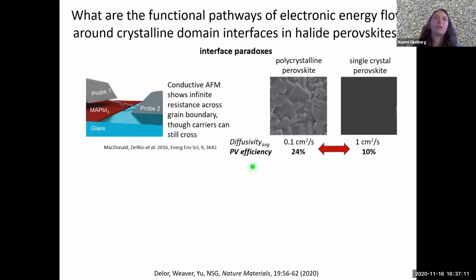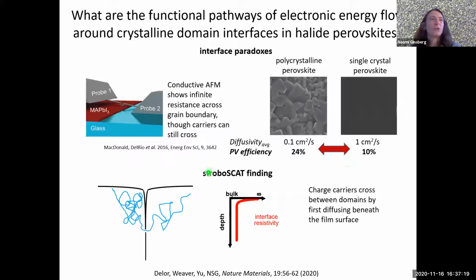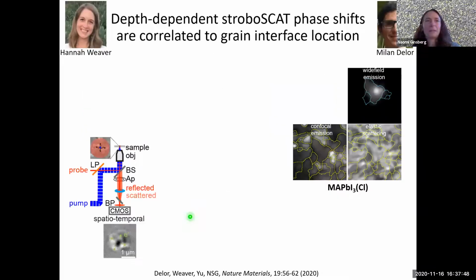That doesn't correlate with the diffusivities that have been measured in these two different morphologies. So we really wanted to explain these apparent paradoxes, and I'm just going to tell you the answer right away and then explain why. What we learned is that these charge carriers that are excited near the surface of the film, when they encounter one of these very highly resistive interfaces, basically have no choice but to move deeper into the material, at which point they can find a region that has a lower resistivity, and then they can move on along into another crystal grain. So let me explain exactly why that happens.